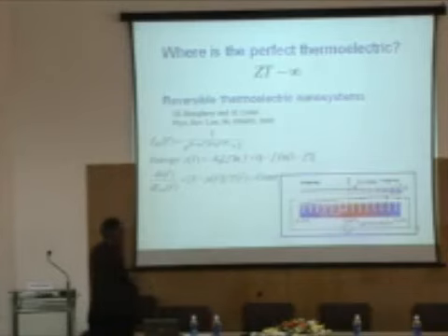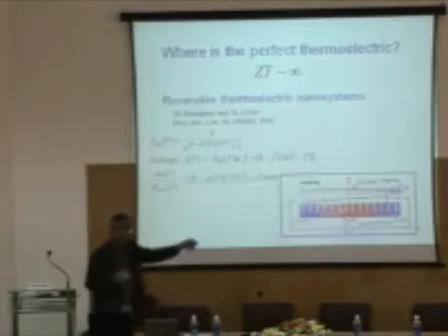So that was their idea: that I can make a thermoelectric where this is the energy level in which the electron is moving, which is, of course, a single energy. An electron doesn't move in a single energy, but I tune as it goes from the hot end to the cold end. I connect it to something, and I change the chemical potential. Then I'll get a perfect adiabatic machine. Therefore, there'll be no loss in the electronic system. So I should get, if there are no phonons in the system, infinity.